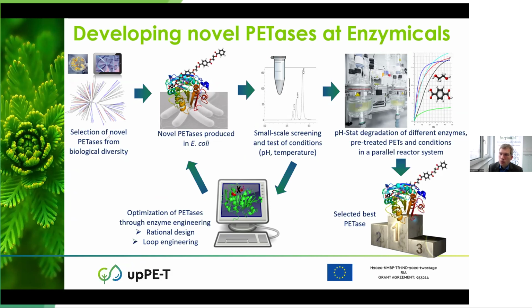The enzymes which seemed useful were further introduced into a cycle of optimization, where we looked at rational design, for example, optimizing positions close to substrate binding, but also loop engineering of these enzymes. From that, we achieved further optimized enzymes, which were then again tested in a parallel reactor system under different conditions like pH values, substrate loadings, and also temperatures.